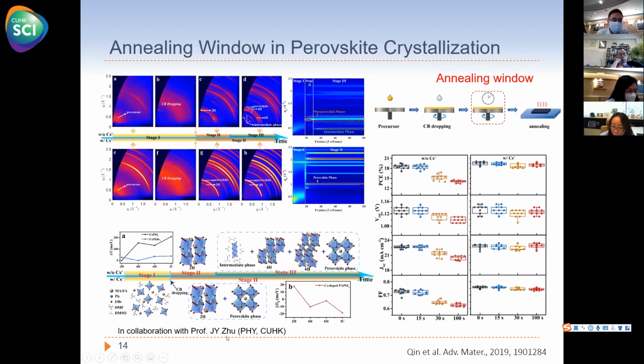So in collaboration with Professor Zhu Junyi in our department, they performed a DFT calculation to help us understand this distinct crystallization pathway and found that the incorporation of cesium will lower the formation enthalpy of the perovskite and promote its formation in stage 2.